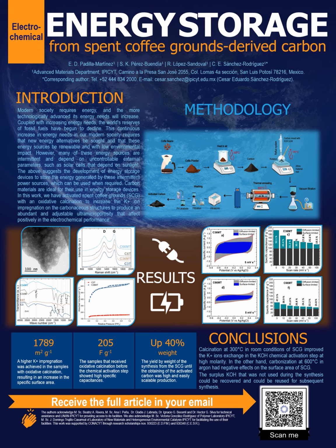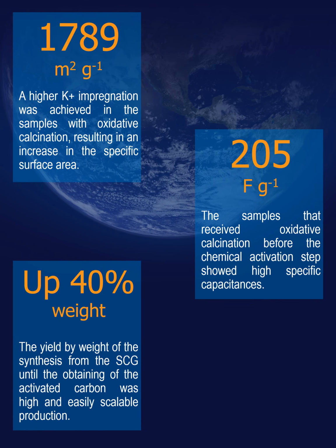In summary, the points to highlight are: we raised up to 1789 meters squared per gram with samples that were impregnated with potassium hydroxide and received an oxidative calcination, obtaining in this way up to 205 farads per gram and maintaining a performance up to 40% by weight from the weight of the base material.